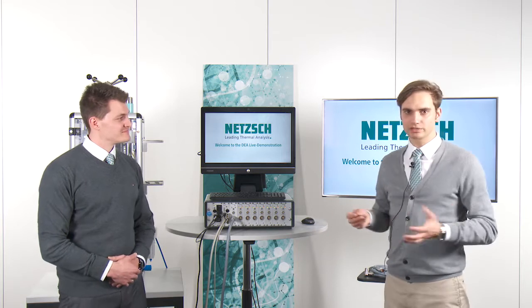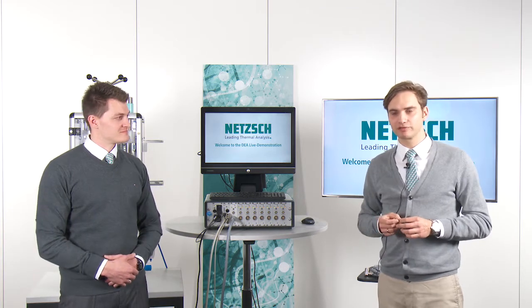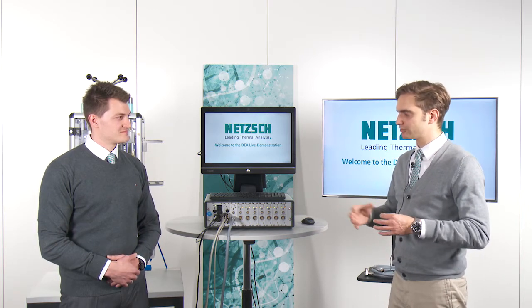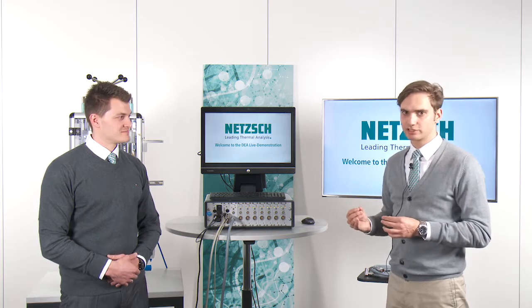Yeah, dynamic mechanical analysis. Okay, dynamic mechanical analysis, short DMA. So we could use a DMA. We also have a NETZSCH DMA 242 E Artemis, or the DMA Eplexor that we could use. And that is very commonly applied, for example, in the aerospace industry. I know that every part that leaves aerospace production is qualified by measuring the glass transition temperature using DMA, dynamic mechanical analysis. And of course, that's also what we can do with our DMA.